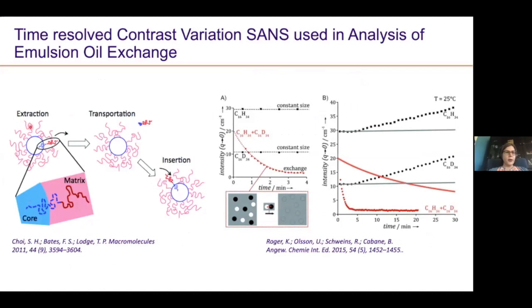And what they've done here is they've actually generated micelles that are prepared out of polymers. And they prepared two kinds of micelles of identical polymers, except that the isotopic composition, or the level of deuterium to hydrogen, in the two populations was different.